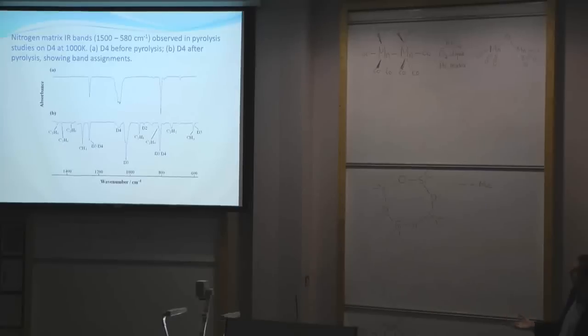C2H6 is obvious from the methyl radicals, but you could also explain how you can get things like ethene coming out there. Very interestingly, D4 is this one with four silicon monomers in it, and D3 is the one that has three silicon monomers in it, and you can clearly see when you heat up the one with four in that you end up with some of the one with three in, which is a sort of, perhaps tangential, evidence that you're getting spitting out a monomer. And you see these hydrocarbons.